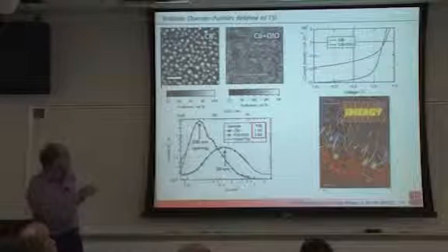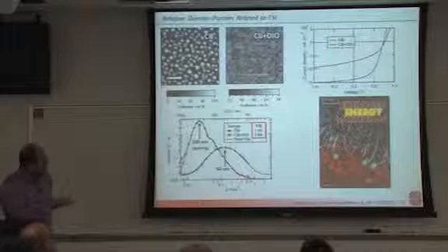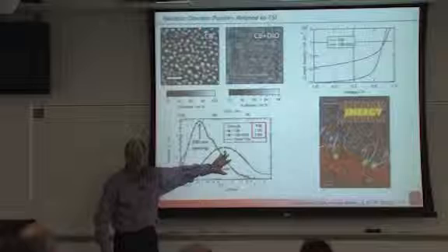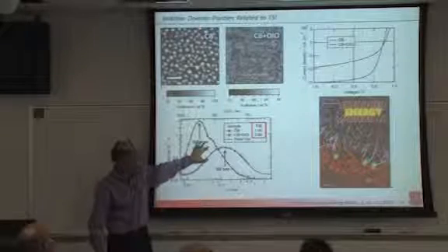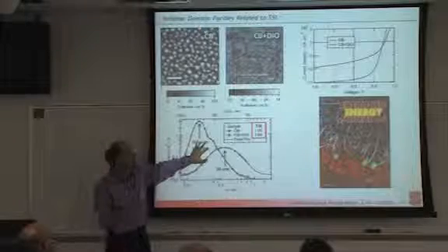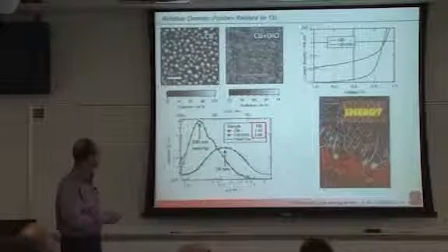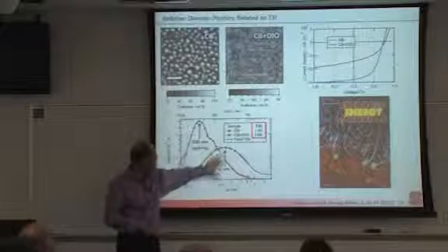So now we do scattering from these samples as well. And so here are the scattering distributions. It turns out it's a beautiful log normal distribution for the DIO. And without DIO, there are two log normal distributions. I'm not quite sure what causes that in terms of the phase separation mechanisms. But nice log normal. The spacing is rather different.